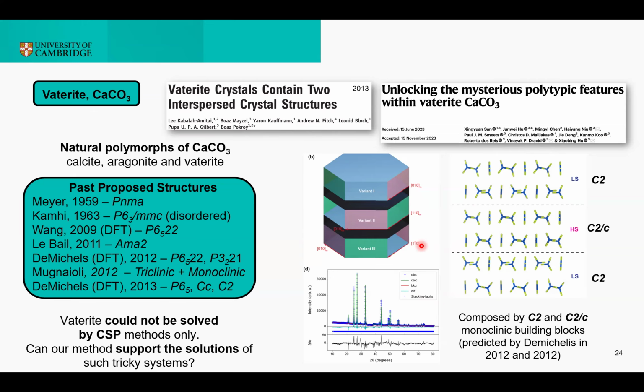And this is a case that, despite the simplicity of the composition, I mean, it's just calcium carbonate, this system could not be unambiguously solved only with powder diffraction, and surely not with crystal structure prediction, since it is not able to capture different symmetry stacking and features like a polytypic network, unless one would use a very extended supercell. Therefore, the question was, what can the method that I'm showing do to help the solution of these tricky systems? And in particular, can this method support experimentalists to deal with these cases?